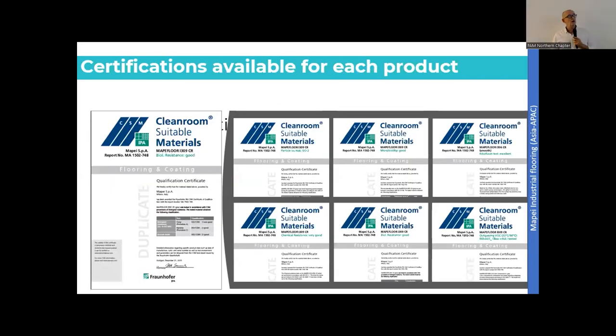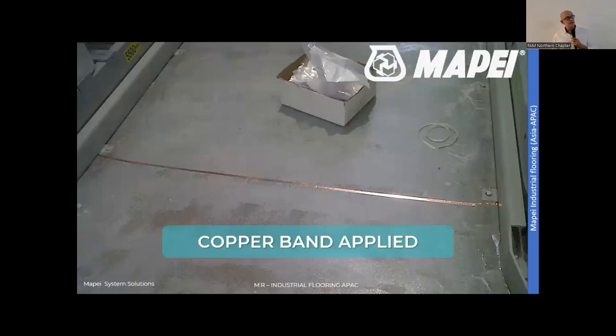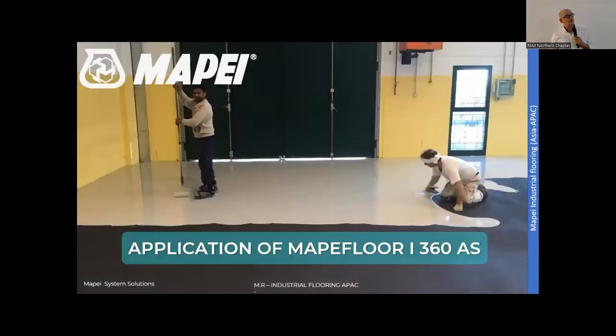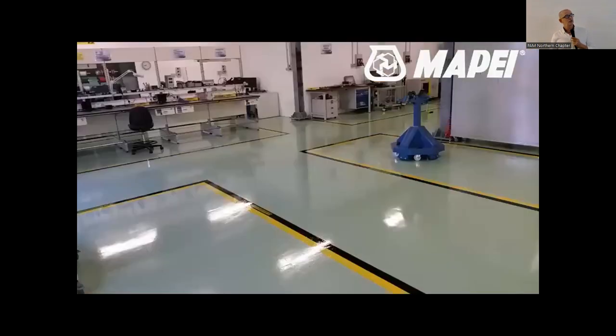So also clean room, of course, after the concrete, you apply a primer. Then we apply the copper tape. After the copper tape comes the black carbon fiber layer, which we're rolling on, and has a certain consistency. Back to the roller, you remember the thickness of the roller, the roller hairs, how much amount of material I have, because this is also calculated, how thick this black layer is. Different companies, manufacturers, have different application techniques. That means some use a thinner one, some use a thicker one. So there are different instruments they are using in order to achieve that. Then you see the black carbon fiber layer with copper tape, and then comes the top coat, which is a self-leveling product, around 1.5 to 2 millimeters thick. A very beautiful impression there.